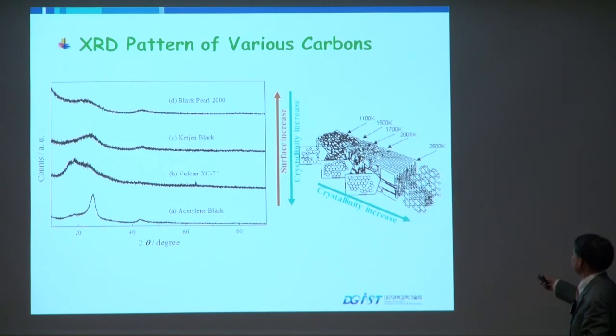And in the preparation of this carbon material, graphitization goes this way: high temperature, and crystallinity always increases this way, and surface area increases this way. So the low temperature carbon has a very high surface area. But when it goes down to this, surface area decreases, but conductivity and crystallinity increase.